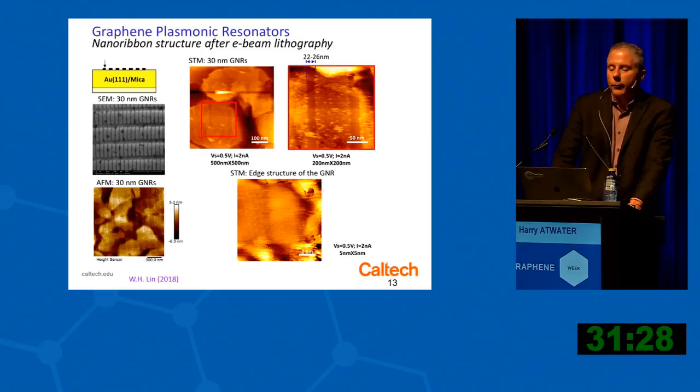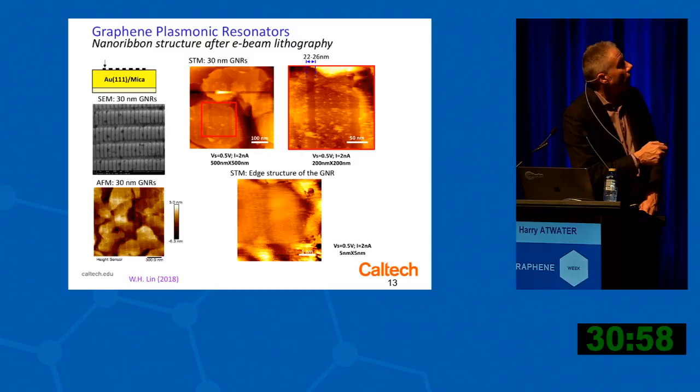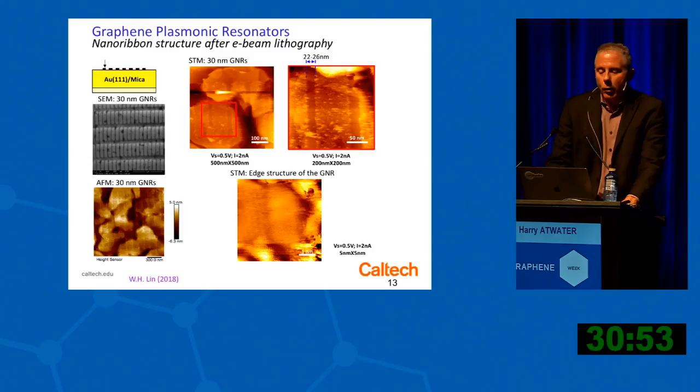So we can also look using nanoscopy, using scanning electron microscopy, atomic force microscopy, and scanning tunneling microscopy, in this case, at an array of graphene ribbons that have been fabricated on a planarized 111 sheet of gold on mica to facilitate the STM imaging. We can see evidence here of the physical structure of the ribbons. You can see here the ribbons are shown as fabricated by electron beam lithography, and we are able to achieve relatively uniform ribbons. Of course, in CVD-grown graphene sheets like this, they are not completely single domain, and so therefore